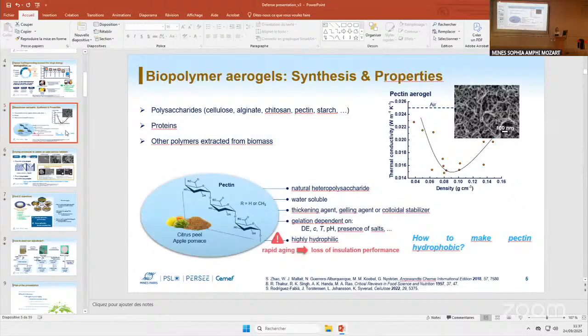We saw that there was a study previously to correlate the properties with formulations, and we tried to select the best materials that had the lowest thermal conductivity. For higher concentration above 3%, thermal conductivity starts to increase, so it doesn't really go lower.